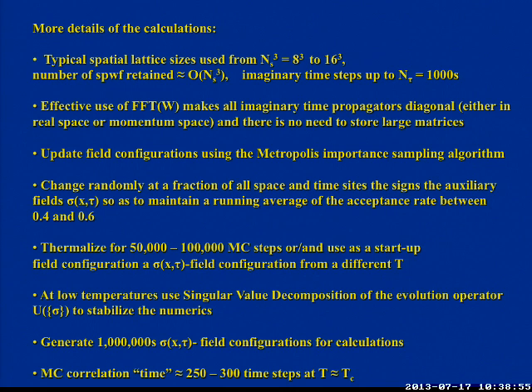How do we do this? We take this field and change the values. Remember, this is plus minus because it's discrete. So for that reason, we have relatively small fluctuations. We change that in order to have an acceptance rate between 0.4 and 0.6. Now, we thermalize at the beginning for about so many Monte Carlo steps. And the correlation time is typically like this. So we generate configurations, but then we have to move so many steps to obtain a new uncorrelated one. So if we do a million, for example, I say somewhere here we have millions of time steps, we basically end up with thousands, maybe hundreds, depending on the problem we are looking at.